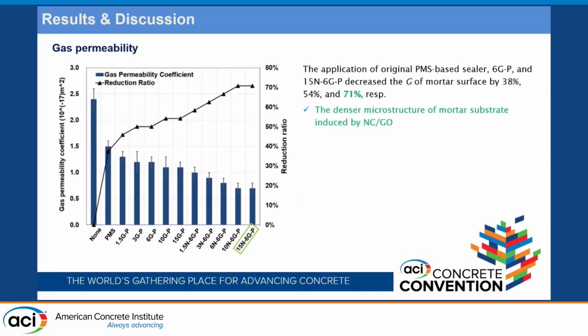Gas permeability coefficient shows a similar trend with water absorption coefficient. Gas permeability mainly depends on the internal transport tunnels. So this decreased gas permeability could be due to the block role played by nanoclay and graphene oxide, which block the pores and then decrease gas permeability. In addition, this decreased gas permeability also benefits to mitigate the rebar corrosion risk, because the oxygen, carbon dioxide, and moisture vapor cannot get into the concrete easily. So it helps to mitigate the rebar corrosion risk.